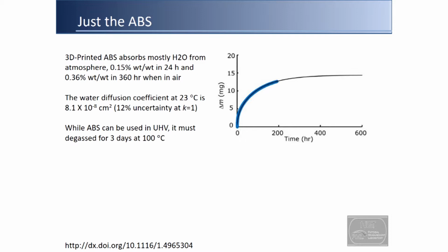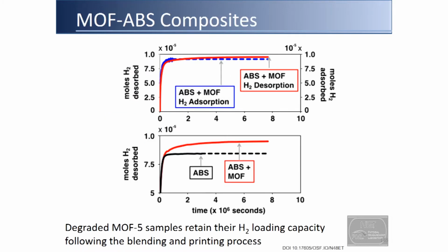The good news is you can still outgas most of this water out. So it's still good enough for UHV applications, so we can do our measurements. But you need to bake it for 3 days at 100 degrees to get rid of all the water. So when you look at the hydrogen uptake, you can load hydrogen, you can desorb it reversibly, go back and forth. If you look at just ABS, the composite compared to that definitely has more hydrogen loading capacity. Now, hydrogen loading capacity was only 33% of what we expected based on theoretical loading capacity of MOF.